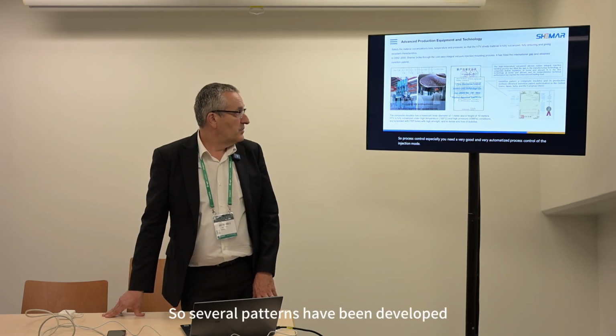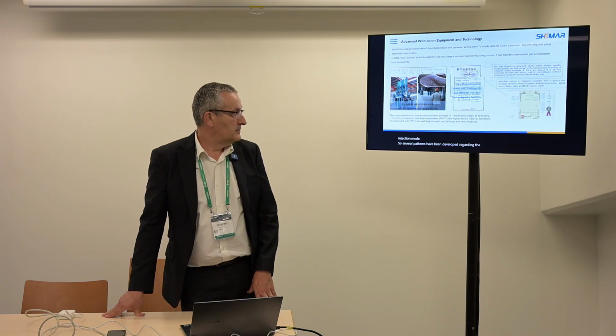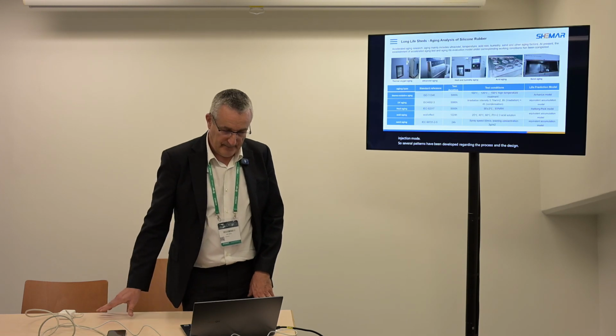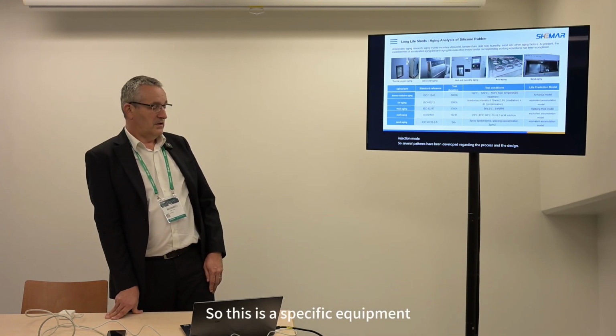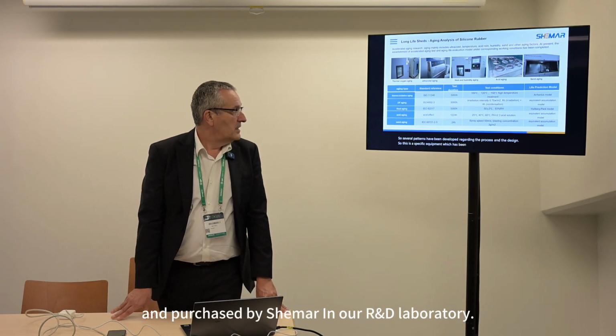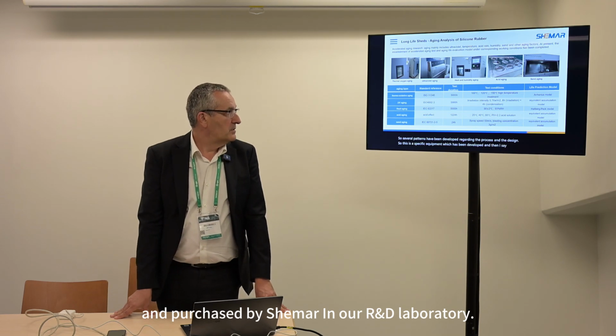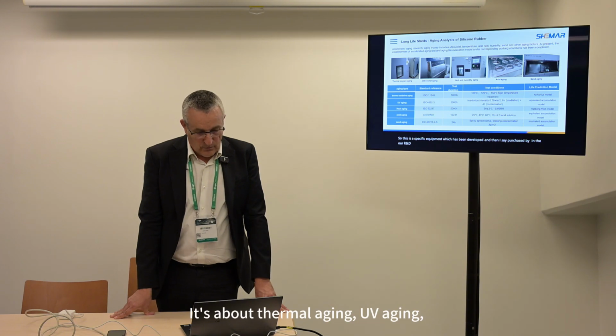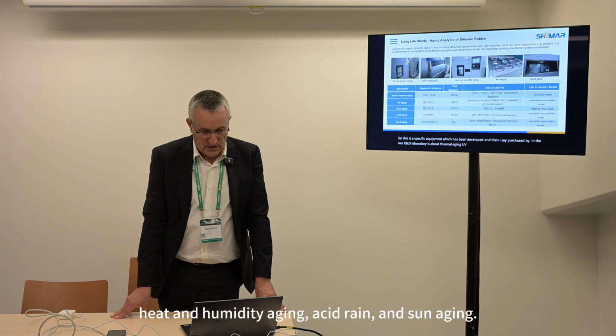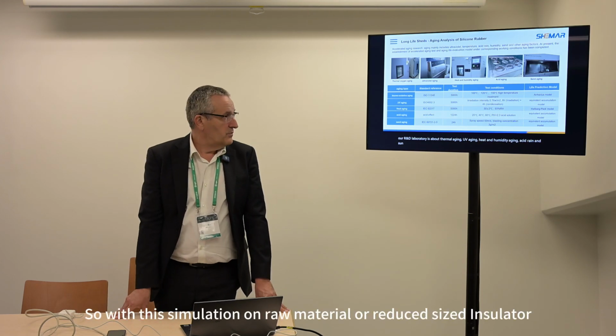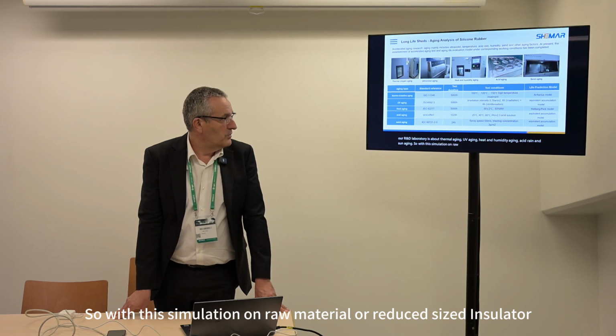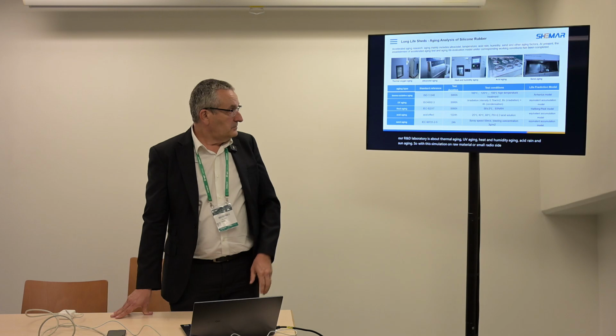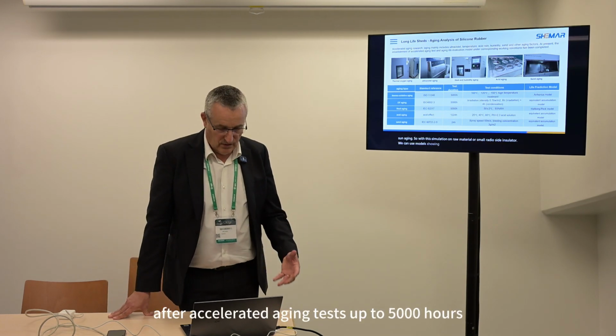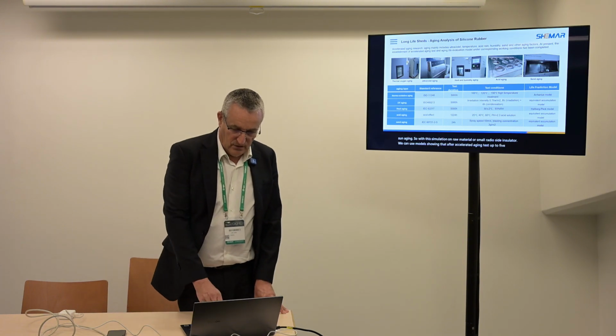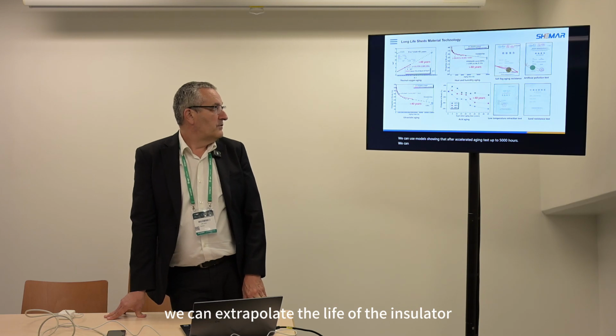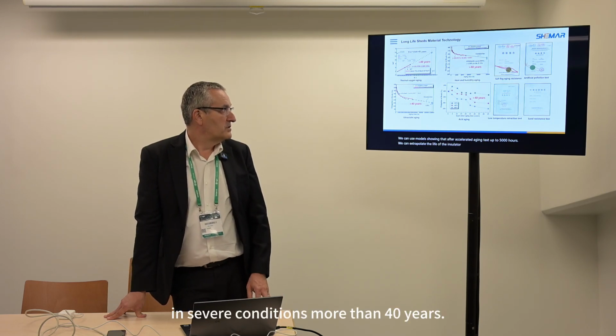Several patents have been developed regarding the process and the design. This is a specific equipment which has been developed and purchased by Shemar in our R&D laboratory. It's about thermal aging, UV aging, heat and humidity aging, acid rain and sun aging. With this simulation on raw material or small reduced size insulators, we can use models showing that after accelerated aging tests up to 5,000 hours, we can extrapolate the life of the insulator in severe conditions to more than 40 years.